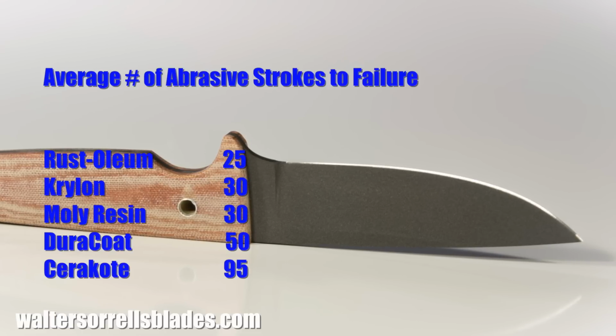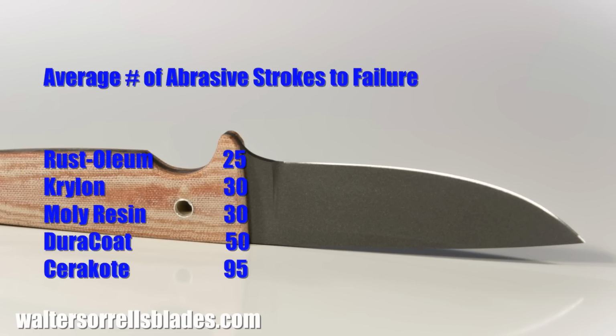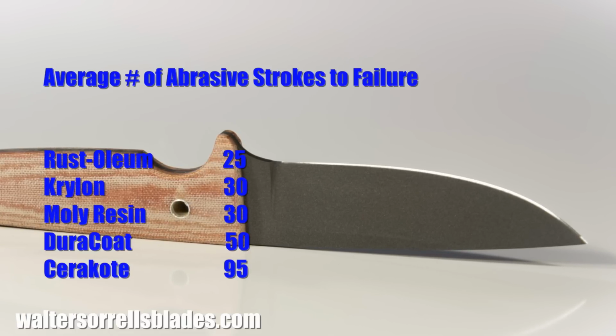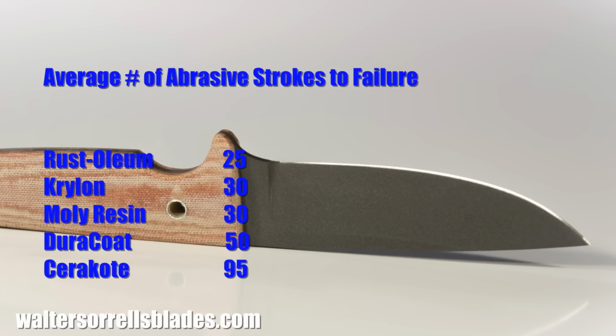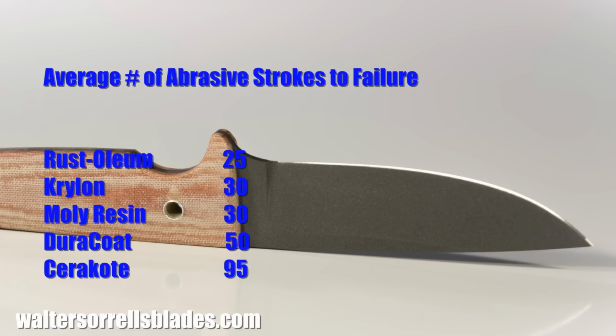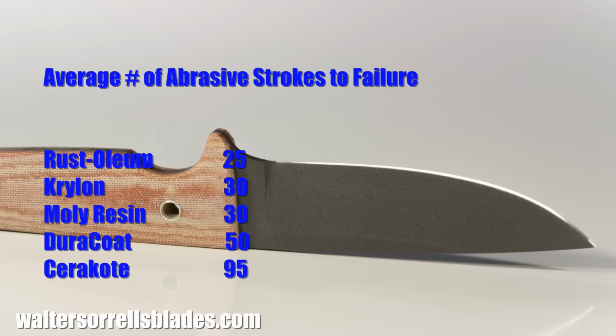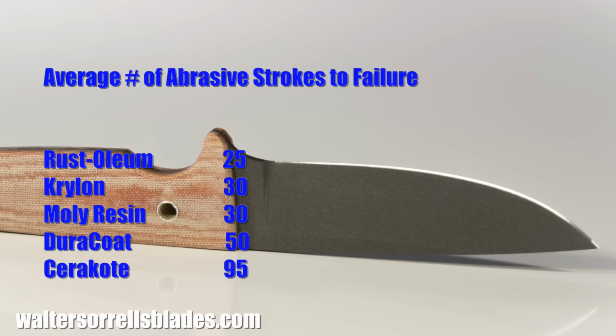Rust-Oleum, for instance, was already showing some bare metal in about 25 strokes, and Cerakote had a little metal gleaming through within 30 strokes. Now, of course, you're not going to line your sheath or holster with sandpaper. This is not normal use. It's just a way of gauging relative wear resistance. So, what am I getting at? There are no miracles here. As I said before, all this stuff will wear through if you put it to hard use.